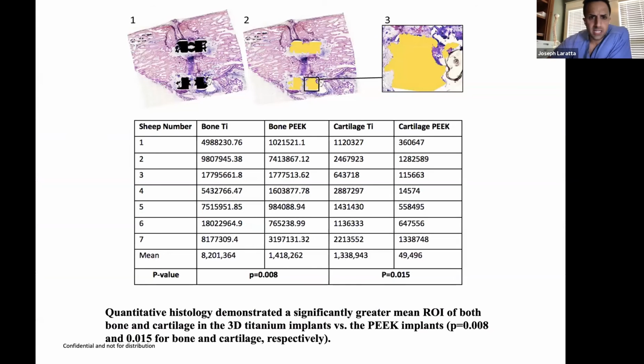We wanted to look at it quantitatively, so we did a quantitative histologic analysis of this, where we subtracted the interbody cage out in yellow here, and the surrounding tissues were measured, discerning those of cartilage versus bone. And what we found was that there was significantly more bone and cartilage in the 3D printed titanium without graft as there was in the PEEK plus allograft, and it was significant in both the cartilage and the bone subgroups.